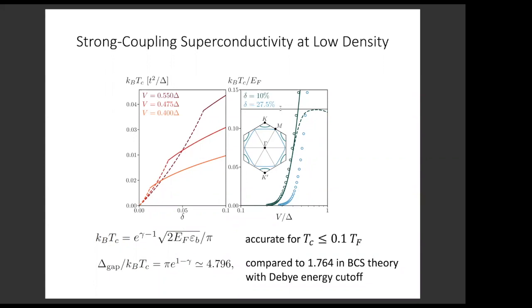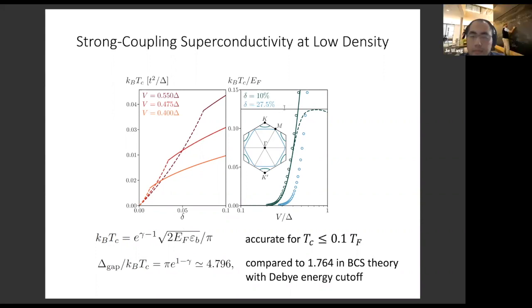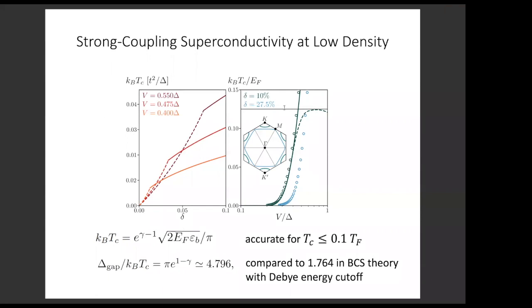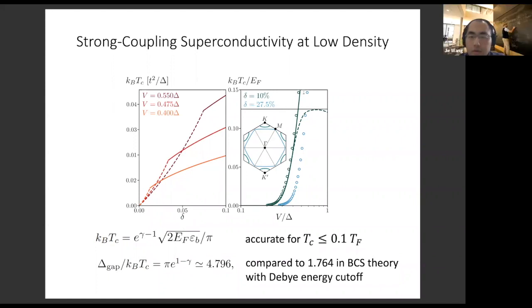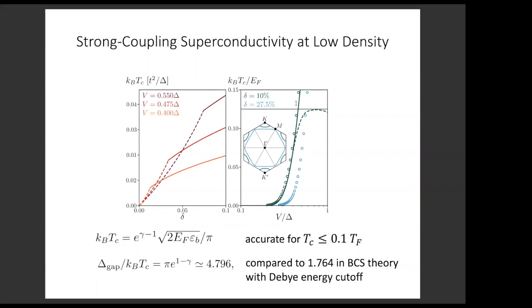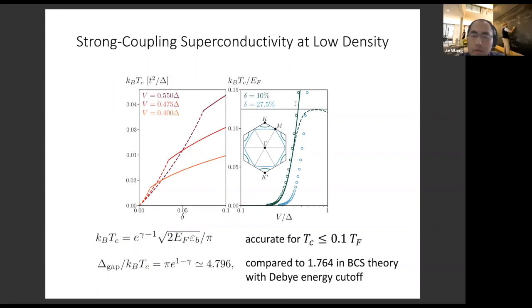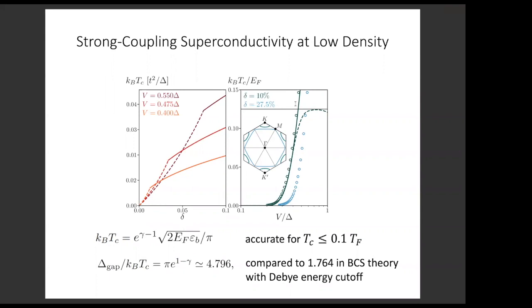Yes. Again, there are real experts on this BCS problem in the audience. But for parabolic dispersion, there's a bound on T_C over T_F. In the BCS-BEC crossover regime, this bound is saturated. And here I'm only showing you the result according to this BCS formula. So why are there two numerical dots above the bound? As I said, these are all from mean field calculation. The solid dots as well as the solid line are obtained from the mean field calculation, and the mean field calculation will fail as you go to the BEC side. As you increase the interaction strength, the quasi-particles also become strongly interacting with each other, and then this approximation will break down. So that's why I said this formula is only valid up to T_C around 0.1 T_F.